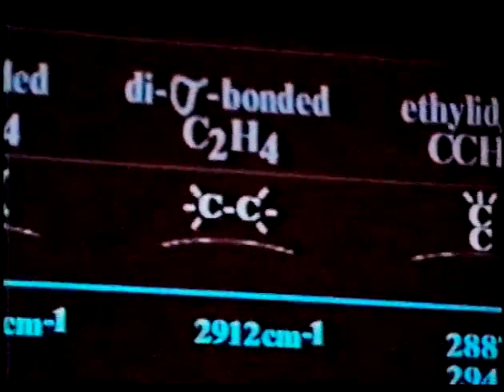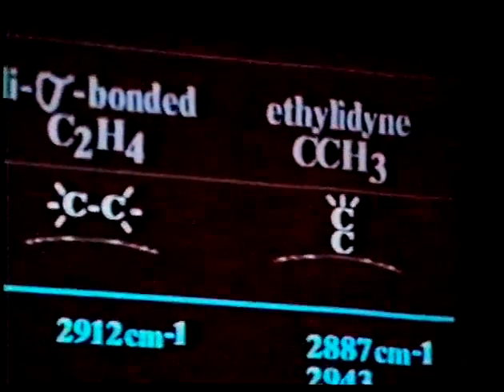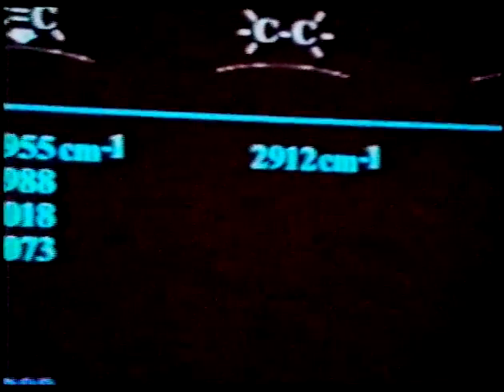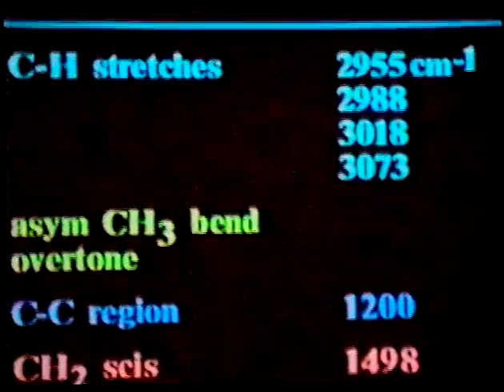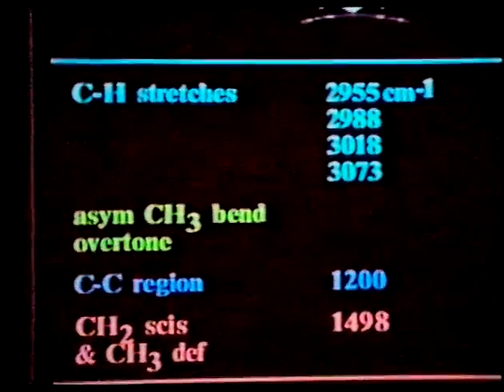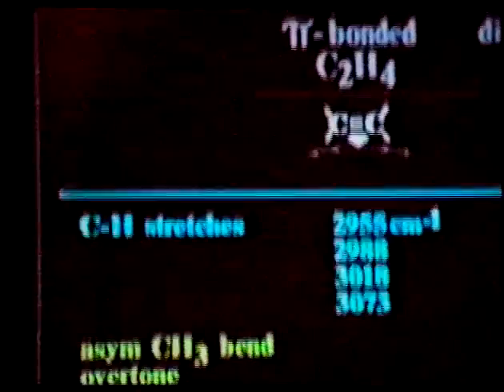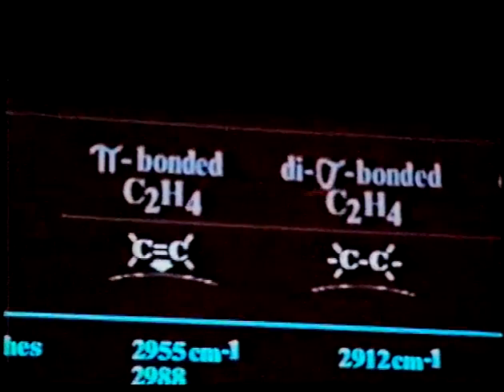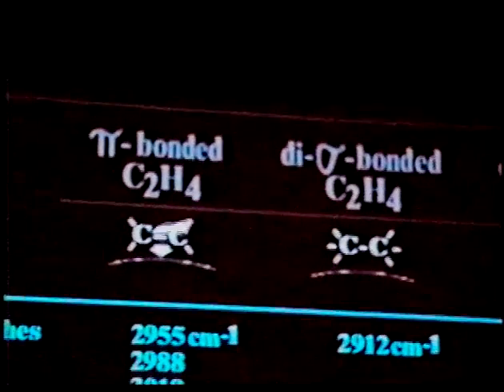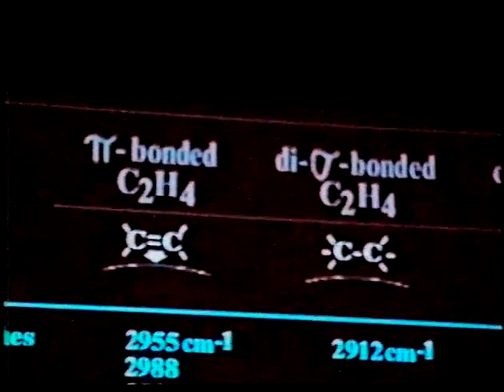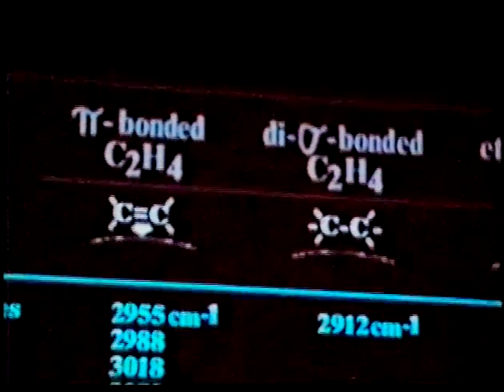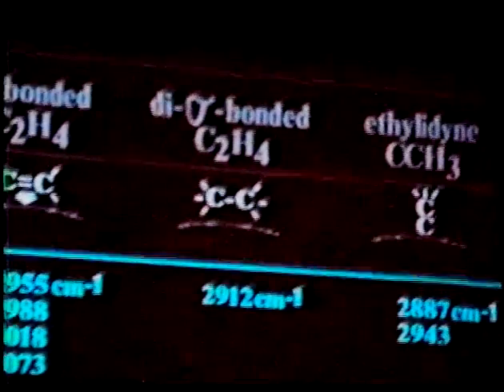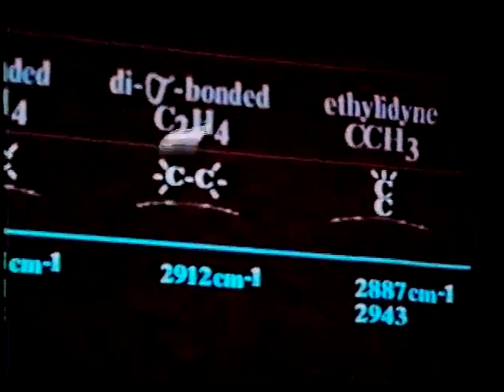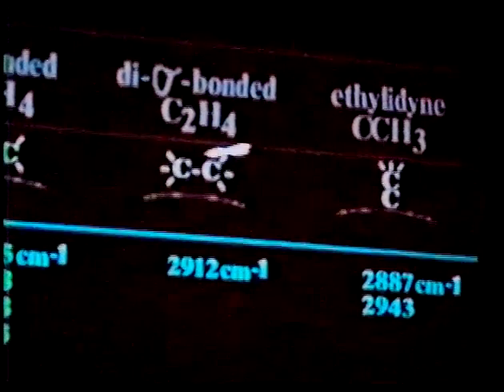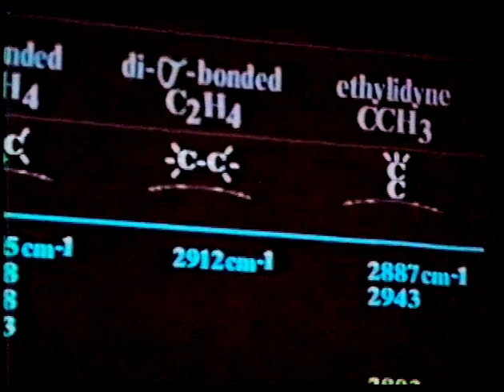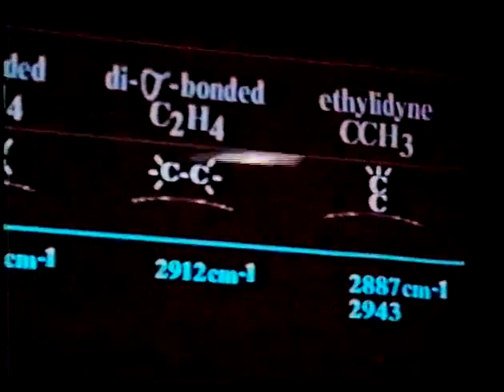It doesn't include some of the kinds of things that you see on single crystal surfaces, and the reason that those are left out is because we have as yet not really observed those. The two principal forms of unreacted ethylene that one finds are pi-bonded ethylene, where the double bond character of the molecule is very clearly retained, and a second type, which is apparently a disigma-bonded variety, where you have now formed two carbon, platinum, or rhodium, or whatever types of bonds potentially, and you've lost this double bond character.